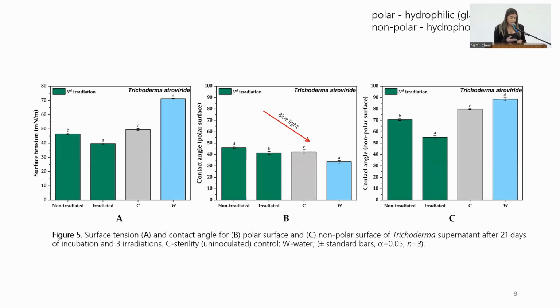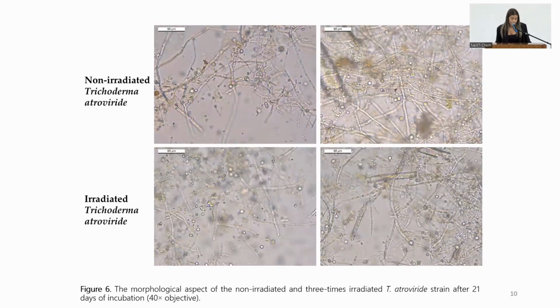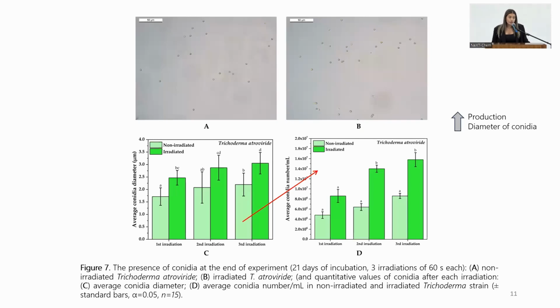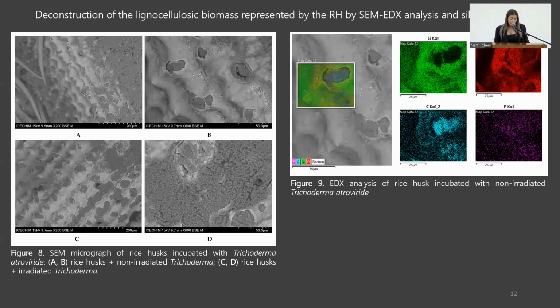The blue light decreased the surface tension and the contact angles of the samples. The contact angles on a polar surface were smaller than those obtained on a non-polar surface, giving an amphiphilic nature to the samples. Here we can see the morphological aspect of the non-irradiated and 3 times irradiated Trichoderma atroviride. Exposing the samples to blue light increased the production and the diameter of conidia in irradiated samples compared to those that were not, and these results are statistically significant. SEM micrographs revealed an intensified lignocellulosic matrix deconstruction due to Trichoderma atroviride exposure to blue laser light, figure 8 C and D, compared to those that were not irradiated, A and B.